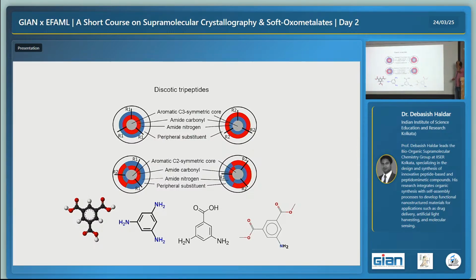Okay, now a little bit difficult or different things. This is also peptide mimetics, but now this is discotic peptide mimetics. It is a disc-like compound, and for that purpose we have two kinds of central core. One is this triamine or this tricarboxylic acid. Other than that, we can use this dicarboxylic acid amine or this monocarboxylic acid diamine. But the thing is that when there are 3 amines or 3 acids, this compound is C3 symmetric. If you replace one acid with one amine in a mixed kind of thing, then you lose that C3 symmetry.